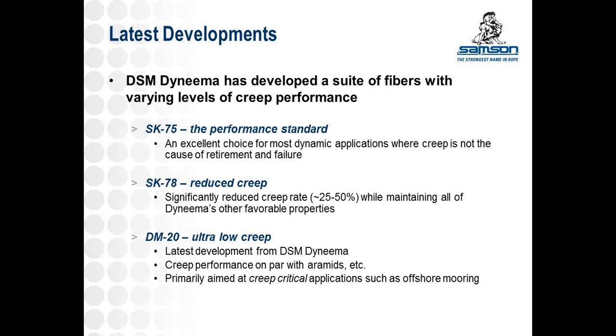They've modified the production process slightly, and it reduces the creep rate to about 25 or 50% of the SK75 creep rate, while maintaining every other favorable property that you find in Dyneema: the strength, the lightweight, the toughness, abrasion resistance, etc. So this is a good choice for applications where it's a bit of a concern, we want to address it, and we can significantly slow down that creep rate and increase the lifetime.